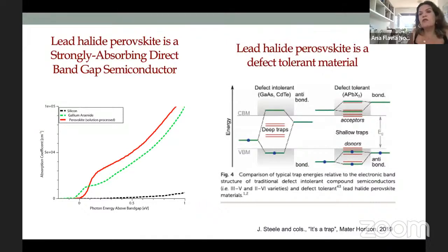The lead-halide perovskite is considered a defect-tolerant material. What do you mean by defect-tolerant material? If you compare with gallium arsenide and cadmium telluride, the first and second generation of photovoltaics, you see here that the traps are located in the mid-gap. It means that these traps are really deep.